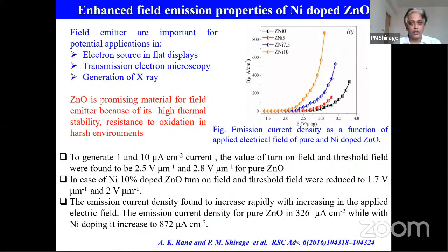So zinc oxide is a promising material for field emitters because of its high thermal stability. I already mentioned that the melting point of zinc oxide is more than 1900 degrees centigrade, so it is very thermally stable. Then there is resistance to oxidation, because if we change the humidity or something, its property will not change. It will be the same. That's why it's very good for the application. So how do we measure this field emitter? We apply the field, then we measure the developed current.